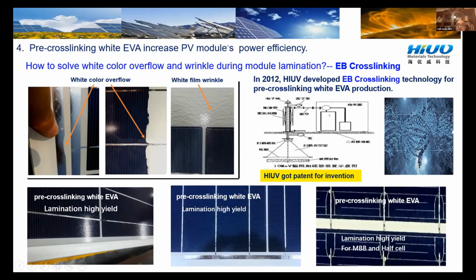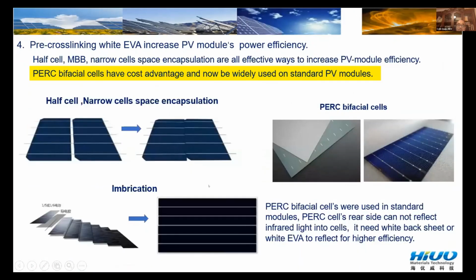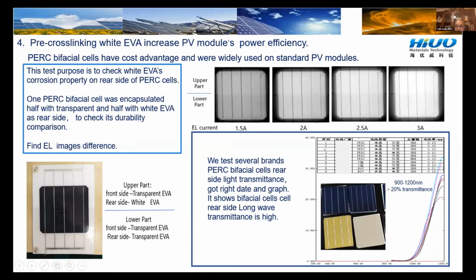So we found the EB cross-linking technology, which can solve this problem quickly. And for modules that have a narrow space, there would be no chance for white EVA to increase power efficiency. In fact, that's not so, because a lot of the bifacial cells have reflectability on this range. On this range, you can see the difference compared with transparent EVA and white EVA on the right side.